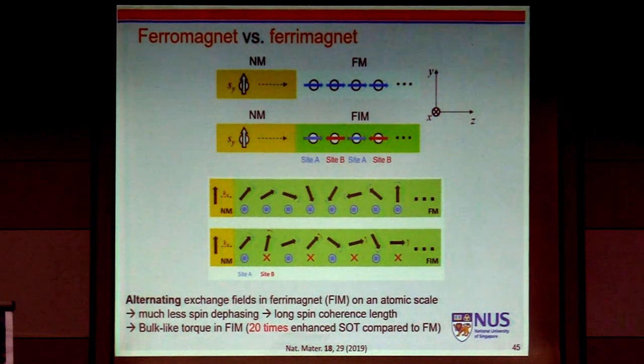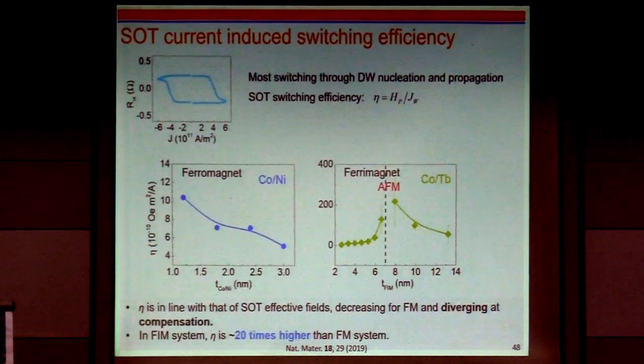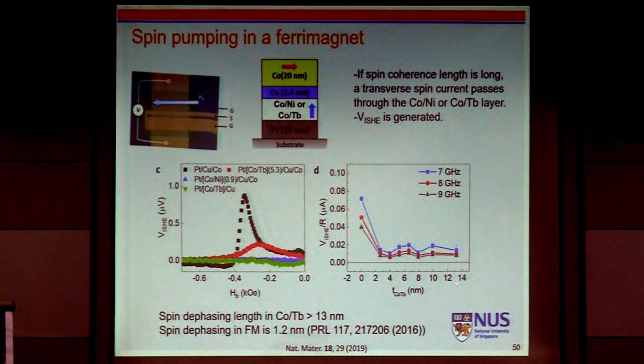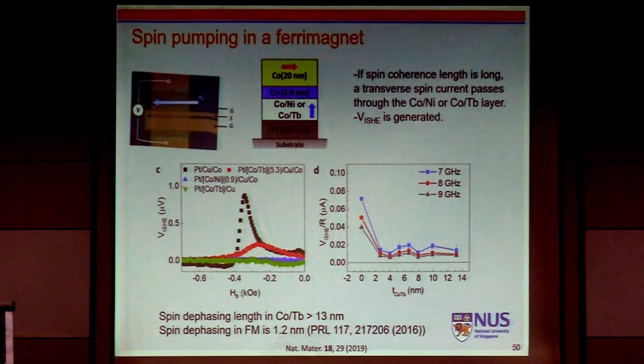So maybe this is what Matthias is measuring. In a really good antiferromagnet, spin will never decay. But of course, in real material, you have defects, impurities, all kinds of dirty stuff, so we have a finite length scale. But even in a metallic sample, look at this: we can measure up to 13 nanometers of cobalt terbium. Spin can survive in a metallic sample, with a lot of conduction electrons here. This is really surprising to me. But in a ferromagnetic material, what we measured is only 1.2 nanometers. You immediately kill all the spin information.